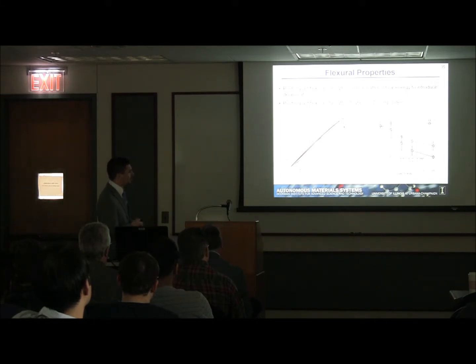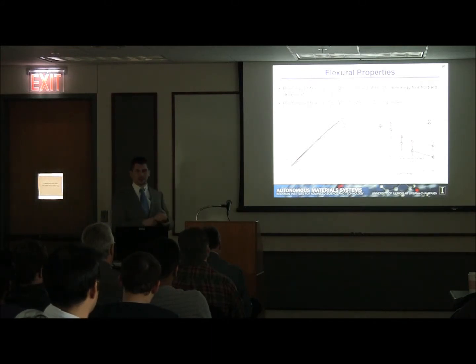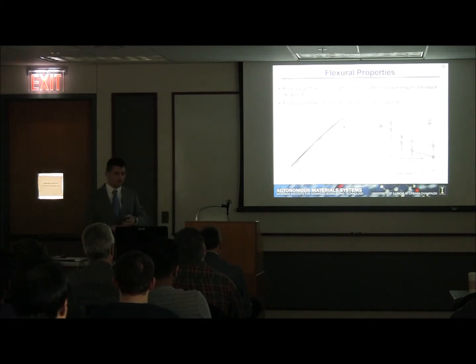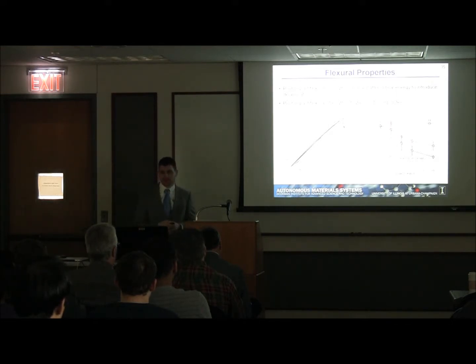However, there is a vertical line here, which isn't showing up very clearly. After we pass some sort of threshold energy to introduce the delaminations, we start to see significant reductions in the flexural strength. And so it's really telling us that this delamination damage mode is driving the reductions in mechanical properties. What's also interesting to note here is that the 3D composites tend to retain significantly more flexural strength after impact damage has been delivered when compared to 2D composites impacted at the same energy.